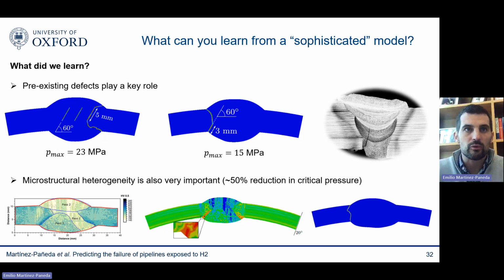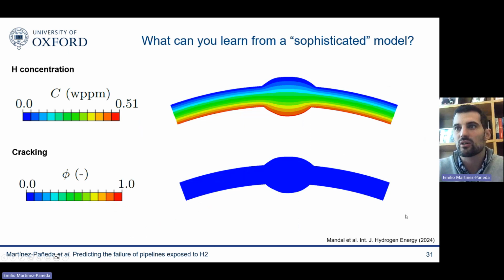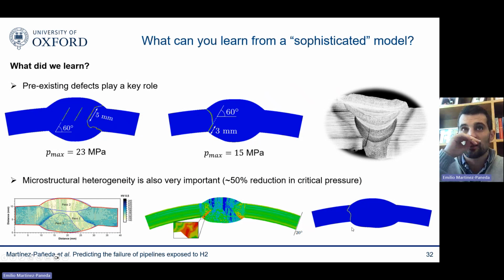So we have done this, and we published a paper on this. It was in the International Journal of Hydrogen Energy earlier this year, where we conducted multiple studies to systematically understand the effect of residual stresses, porosity that comes into the weld, but mostly pre-existing defects. We did a systematic study to understand various combinations of pre-existing defects that we know exist in those assets. And interestingly, we found that a flaw that is 3 millimeters long and axial in the heat affected zone can deliver a critical pressure failure of 15 megapascals, which is not too far away from large-scale tests that have been done under very similar conditions.